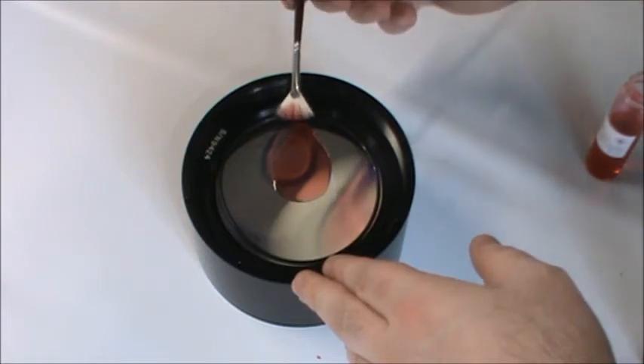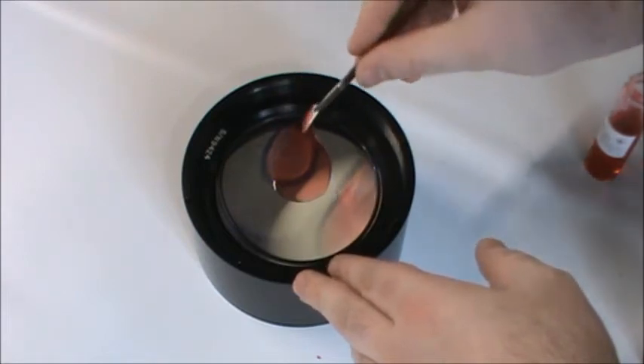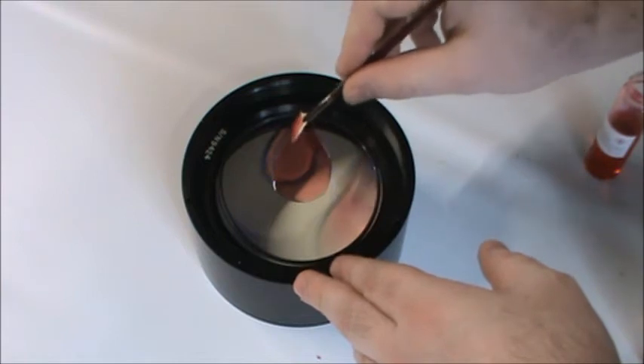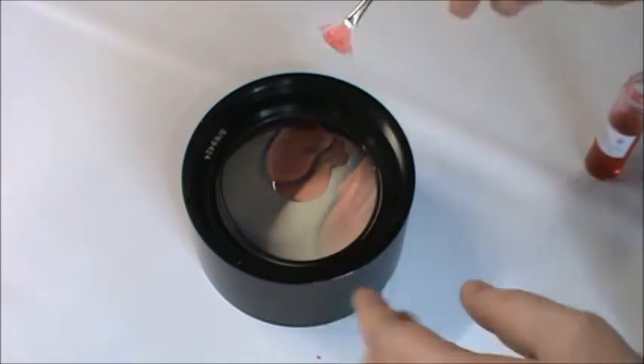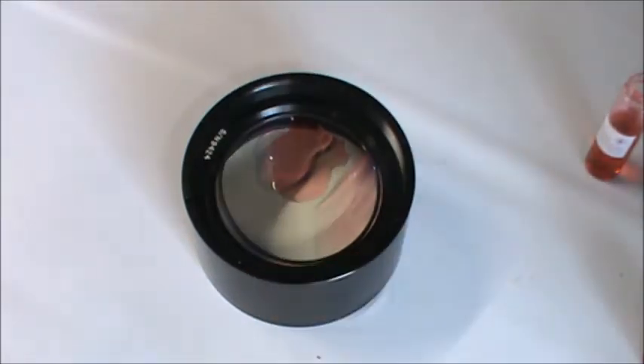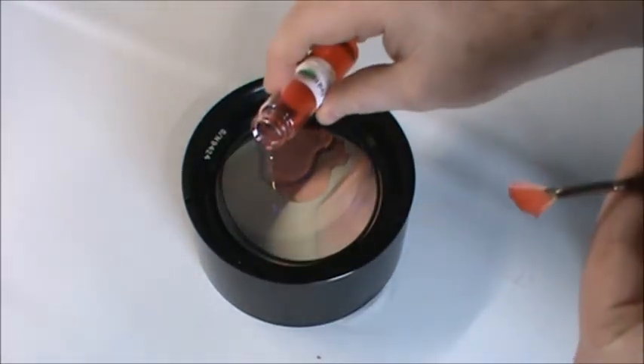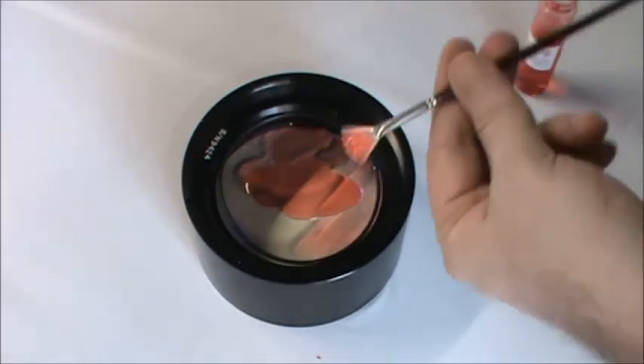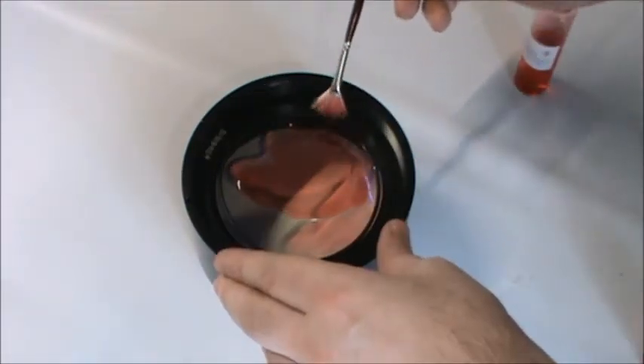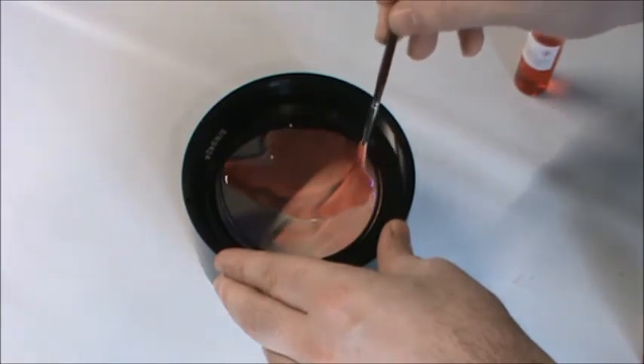To do so, use the surface tension between the liquid polymer and the brush so that the brush never touches the glass. Spread the polymer until it runs into the o-ring and there is an even coat. Add more polymer as necessary. The liquid polymer will interact with the dry polymer on the o-ring to create a vacuum-like seal.